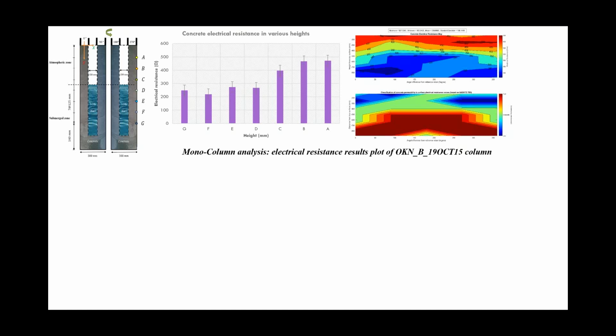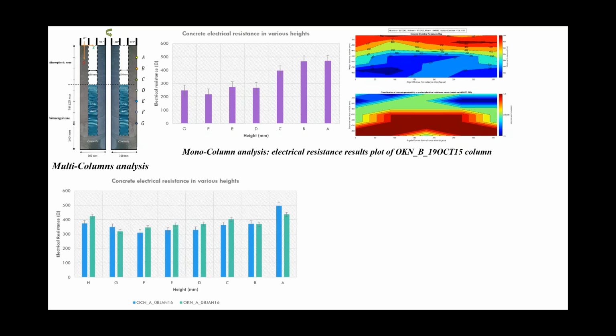Then I started comparing 2 different types of columns, and as you can see, the one that has been treated with admixtures showed higher resistivity in most of the spots, which is a good indication because it shows that you have less permeable structures. This is expected because the admixture blocks those pores inside, and there is going to be resistance for the concrete to allow the electrical current to pass. And this is also for 10 of the columns.